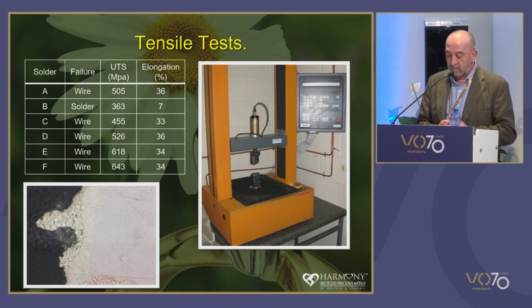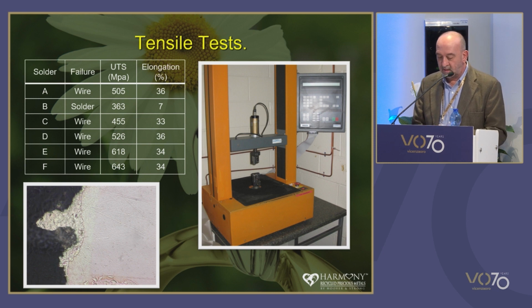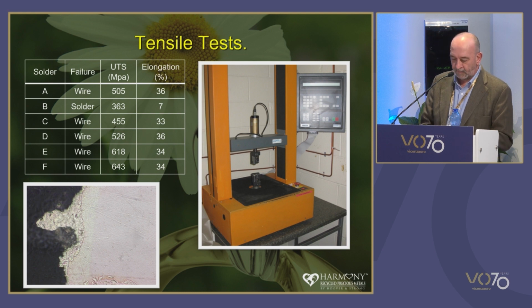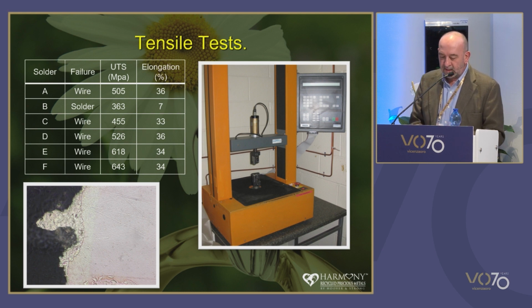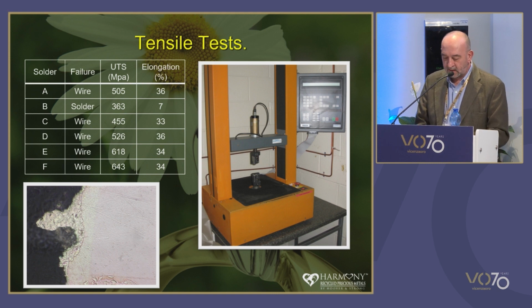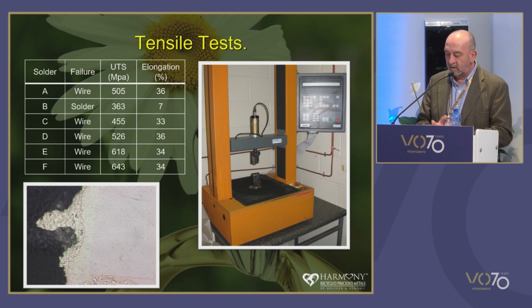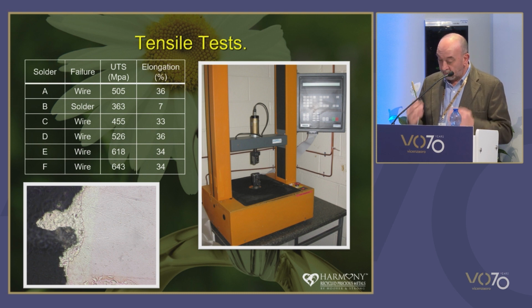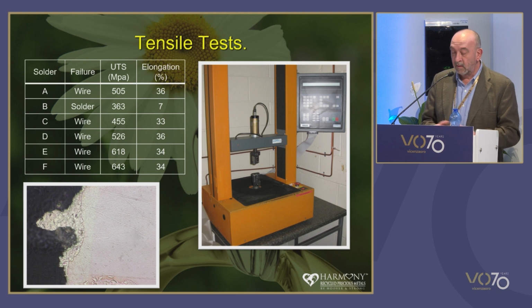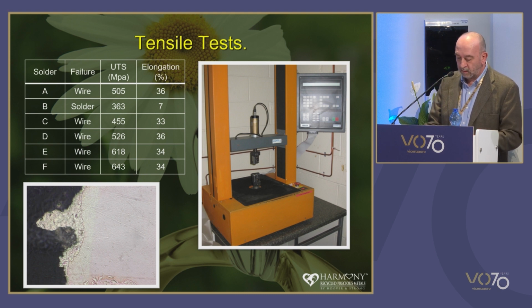And the results would suggest that mechanical properties of the solder have been compromised due to design considerations to achieve the desired melt range and the desired color. So the third test we did was to simulate a ring sizing operation, and this is one of the most common jewelry repairs there is. So sizing is done by either removing a section of a ring shank and soldering the ends together, or inserting a piece of sizing wire into the shank and then soldering this. Either way, it's a typical example of a butt joint.